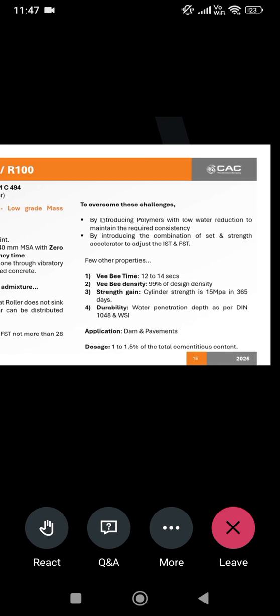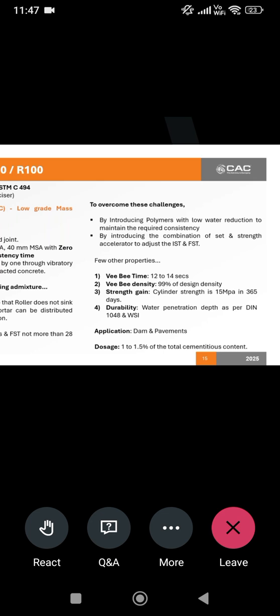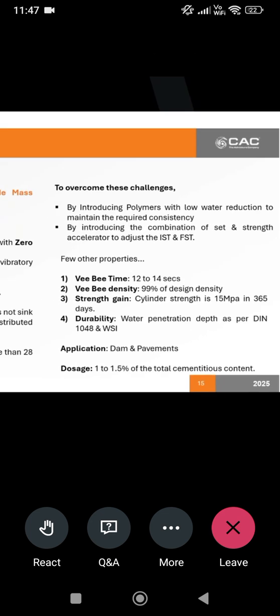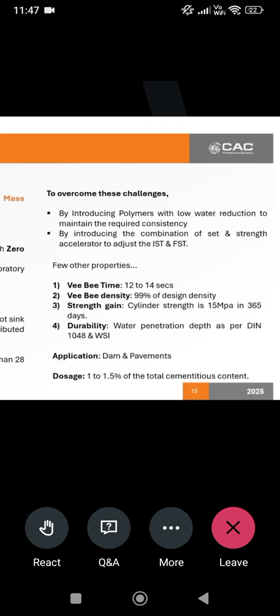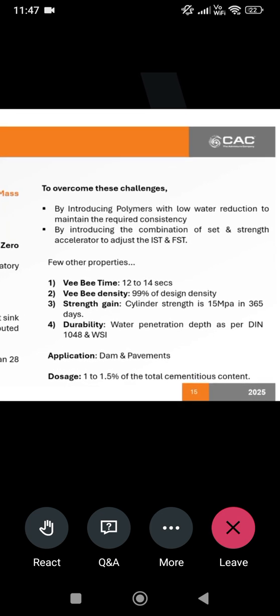How are we doing these things? By introducing polymer with low water reduction to maintain the required consistency, right? And by introducing a combination of set and strength accelerator. Basically strength accelerator, not set. If you put set accelerator, you will not get 22 hours IST. The set and strength accelerator adjust IST and FST, right?